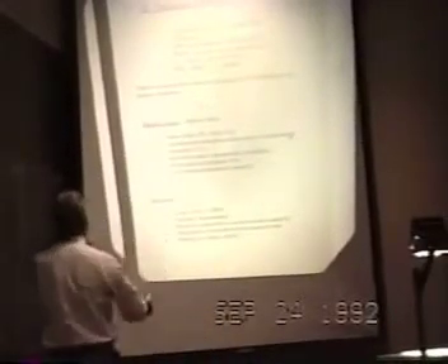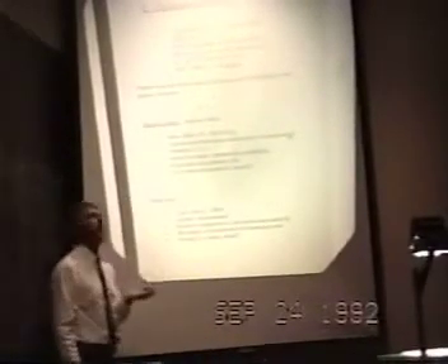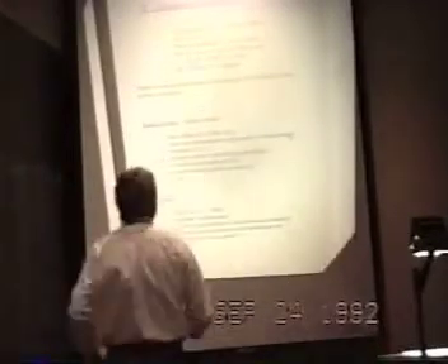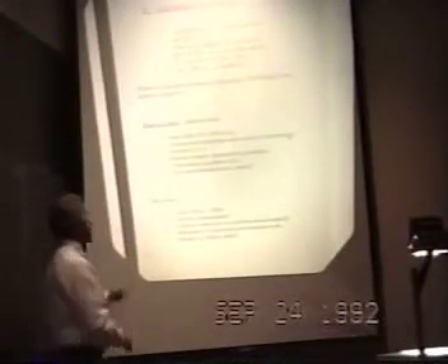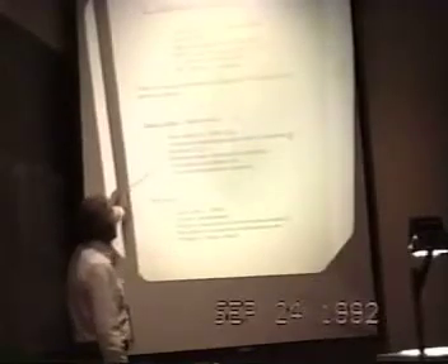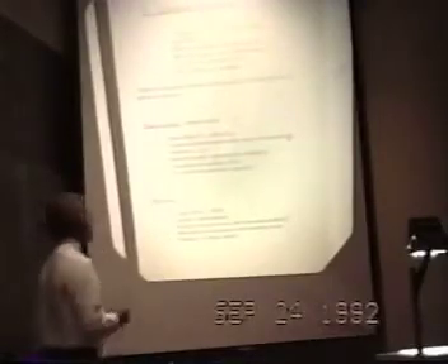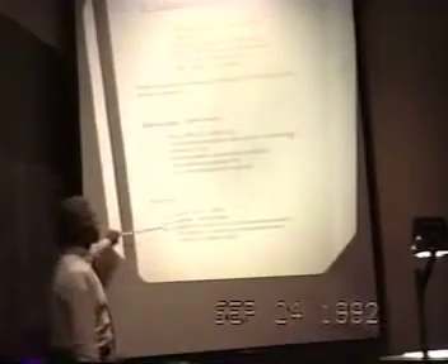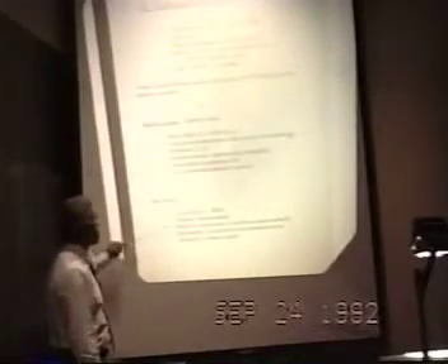Peak bursts, these are large effects, greater than 300% of the input power. They appear to initiate spontaneously. Clearly they don't initiate spontaneously, they themselves must be causal. We don't know what the parameters are that initiate these heat bursts. They are relatively insensitive to current density, unlike the baseline excess, and may even survive small amounts of anodic charge, that is stripping, reduction of the deuterium to palladium ratio by electrochemical means. May or may not appear in conjunction with the baseline observation.